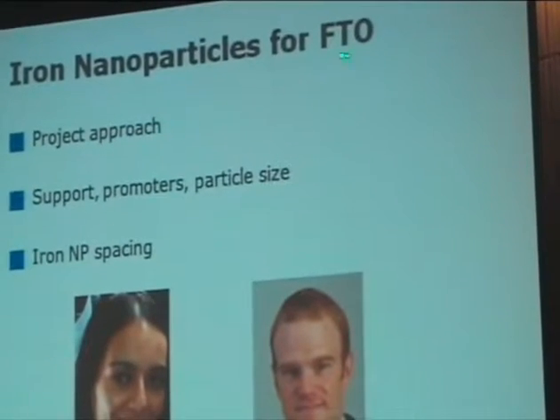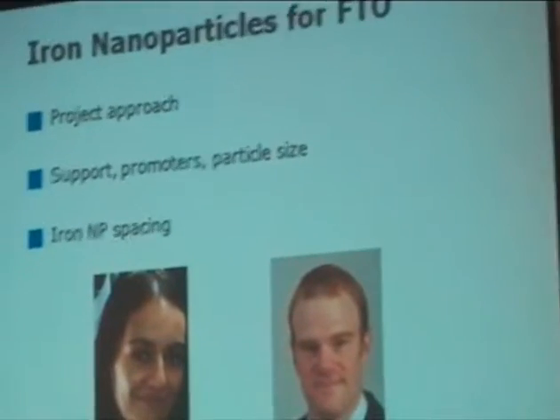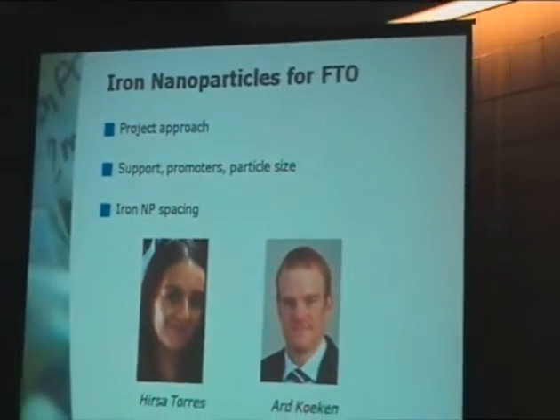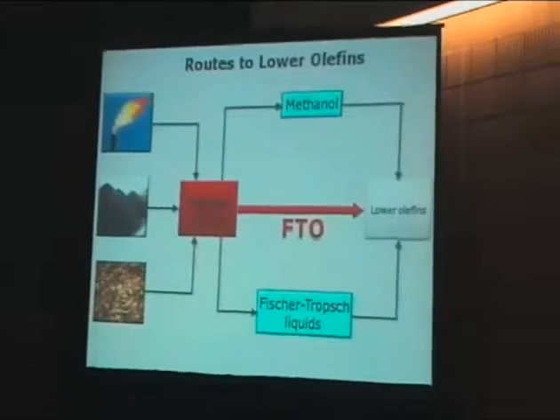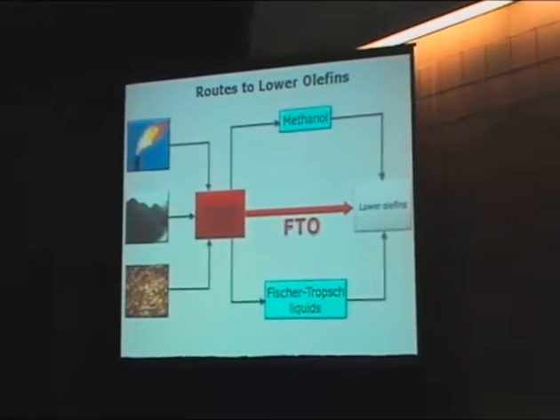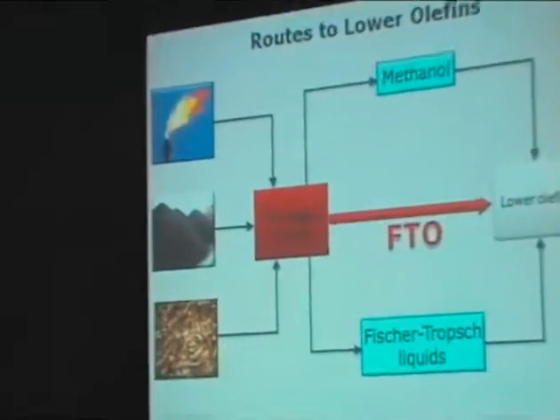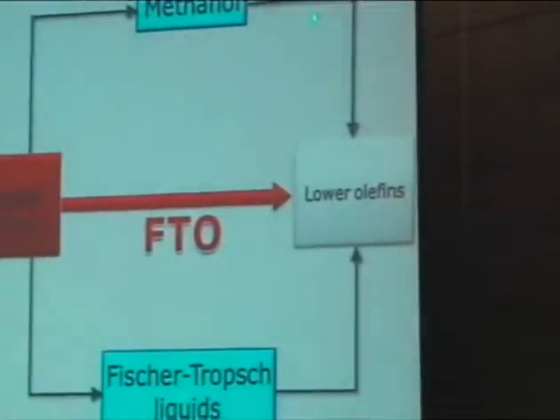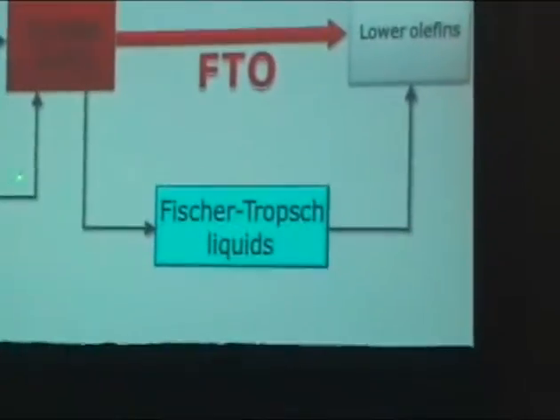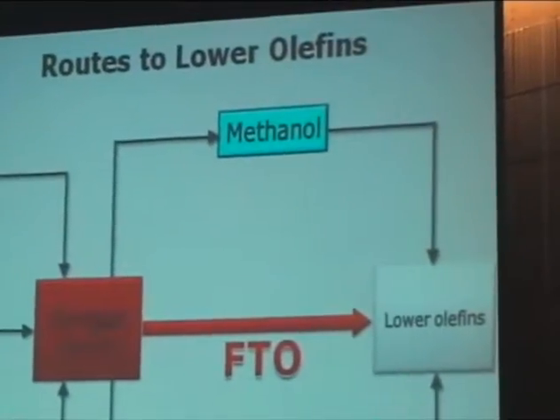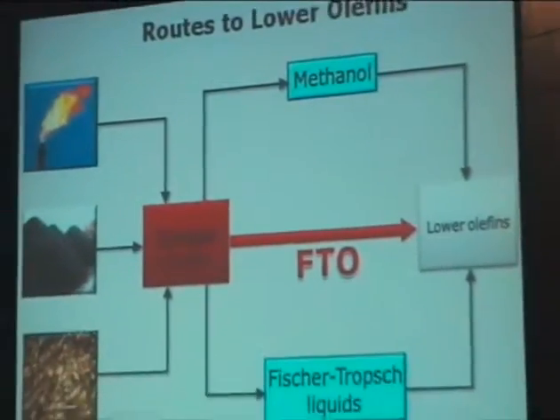And we applied it for so-called Fischer-Tropsch to olefins. Hirsa Torres and Ard Koeken have been contributing and doing this work. Again, a variety of feedstocks. We make syngas, and if you want to go to lower olefins these days, we go either via methanol, as practiced now in China, or we go via FT, the FT naphtha fraction in particular, because it makes poor gasoline. So that's fantastic steam cracker feedstock. So this is both in operation, and this could be an alternative. So we were studying this direct conversion of syngas to C2 to C4 lower olefins.